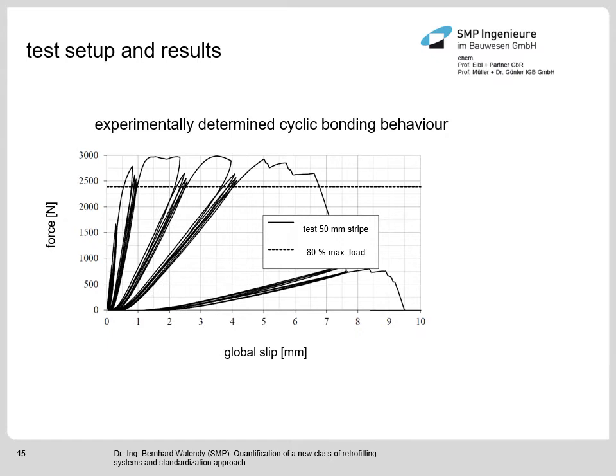This is typical for fiber reinforced polymers, and this is completely different to reinforced concrete with steel, for example. And this has severe consequences in terms of ductility of the systems. But this is something I want to get back to in a slide where I want to introduce some numerical parameter studies which have been conducted in order to analyze this aspect of the very narrow hysteresis.